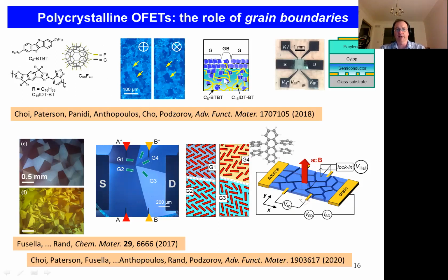What happens in these blends is that the small molecule film segregates on top and crystallizes, forming these nice polycrystalline films. We top them with a gate insulator and a gate, producing these top-gated transistors, and measure charge transport and Hall effect.